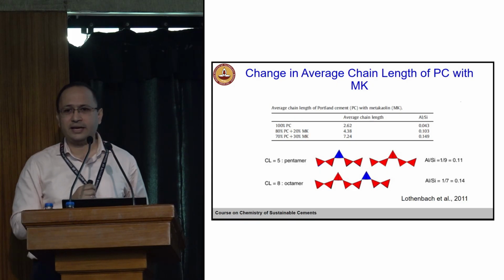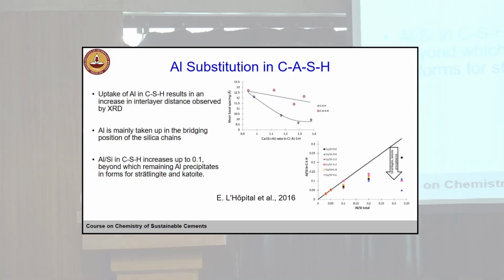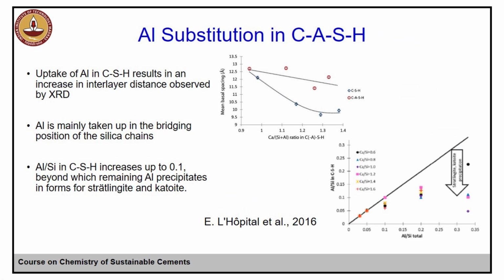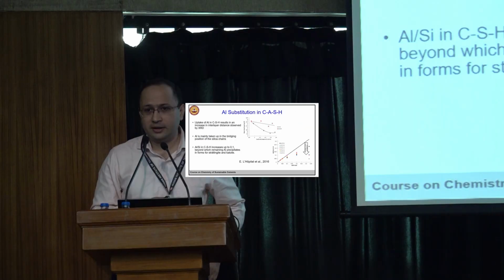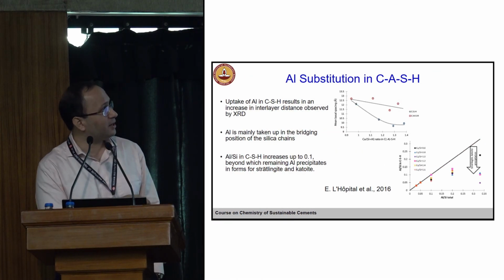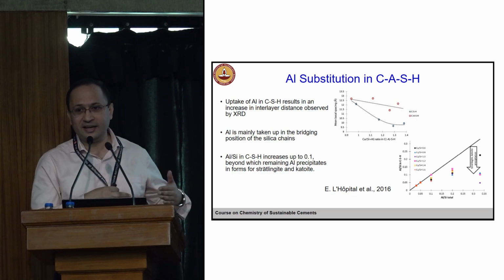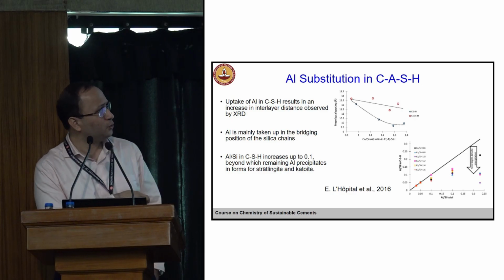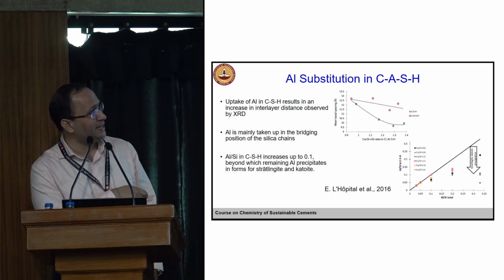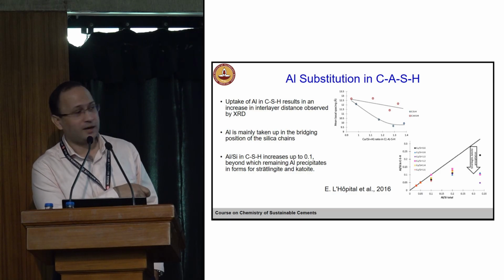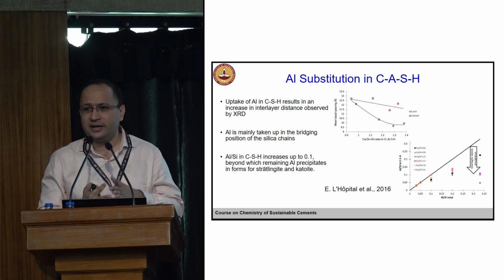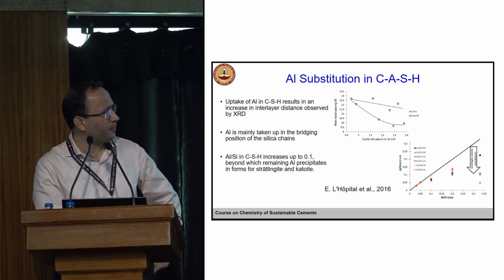Now we understand that the calcium to silicon ratio is going to decrease when we use these SCMs. So what happens? First, it's pretty clear that if we are incorporating alumina in the CSH structure, that changes the basal spacing, the distance between these layers. So you clearly see as the C to S ratio is decreasing, let's say this is the conventional one, as this is decreasing, your basal spacing is increasing, right? So it happens in both. If you look at CASH and CSH, it kind of makes sense, right? Something is getting incorporated, it's affecting the interlayer basal spacing.